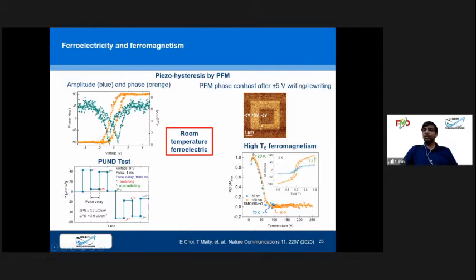And then again we apply minus 5 volt, then we switch back again. So that means the switching is possible. And this is a pulse test, which is called positive up and negative down test. So if we apply a pulse voltage, then the polarization is there. Then you get a remanence also. And if you apply the negative pulse voltage, it goes in the negative direction.